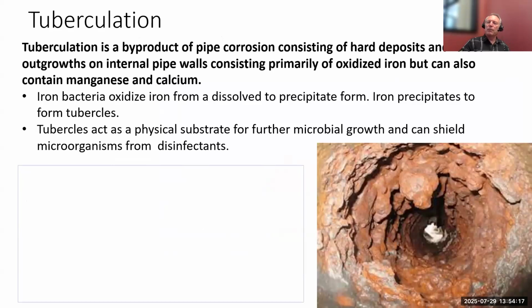Tuberculation is a potential outcome of corrosion when you have iron pipes, especially something like cast iron pipe. What's really happening here is iron bacteria are involved, and they are helping to oxidize that iron and form a precipitate. When you see the tubercles growing, that's a combination of bacterial action and the corrosive action forming basically rust. And once you get tubercles growing, it acts as a substrate that facilitates more bacterial growth. And as you can imagine, a pipe that has tuberculation like this is going to significantly affect the amount of horsepower it takes to push water and the flow that can go through that pipe.